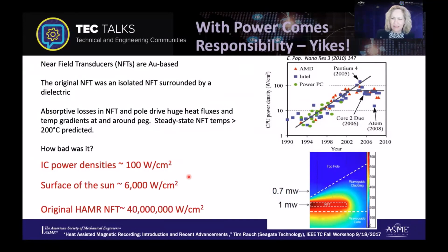When someone's talking about the surface of the sun in a reliability presentation, it's probably not good, and particularly if you're higher than that. It wasn't because the laser powers were so high; we're talking about tens of milliwatts. It's that the size of that peg is so incredibly small, a 40 to 50 nanometer square peg. It's a really, really small area. So it's a moderate amount of energy in a very, very small space, giving a very high density that needed to be dealt with.